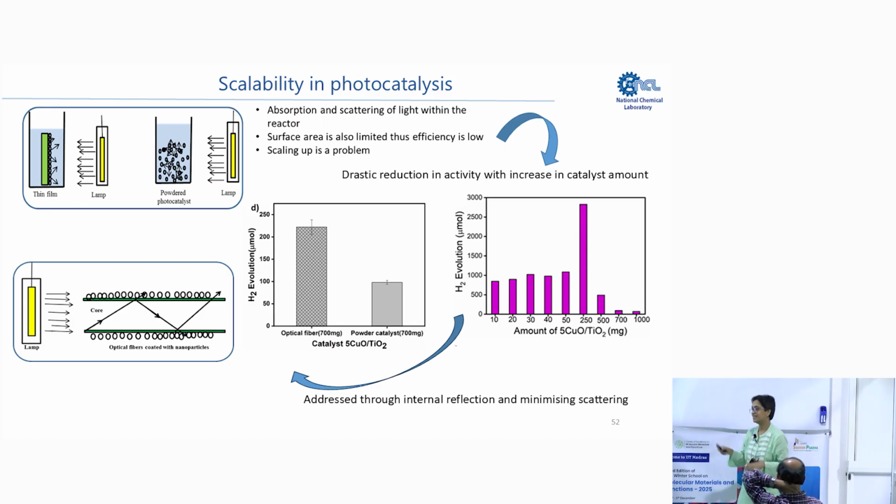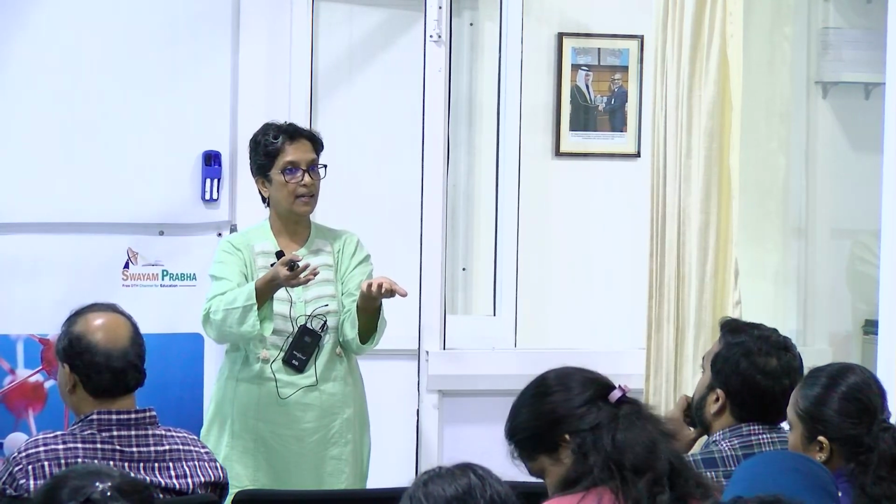Okay? Yeah. Ma'am, how do you design the catalyst to avoid metal leaching or sintering in harsh conditions? Yeah, so one method is encapsulation, which I talked about, right? You encapsulate, and then it is not going to move around; the collisions and Ostwald ripening do not happen, and then you will be able to control it. We could control it, even gold, palladium and all that, you saw that it could be controlled around 3 to 4 nanometer. That is one method.